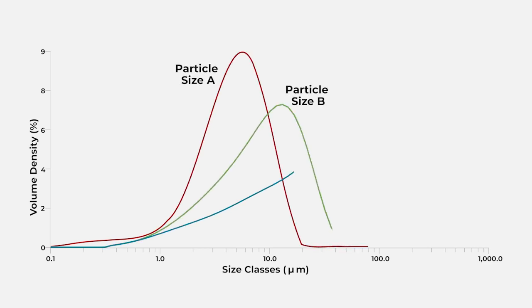As you can see in this example, 3 separate particle size grades of mineral filler have different size distributions. When we optimize the ratio of the 3 grades, you can see we get an overlap of the sizes to fill the interstitial space more completely between the particles. Optimizing the loading of interstitial spaces improves particle contact kinetics, thermal conductivity, and viscosity.